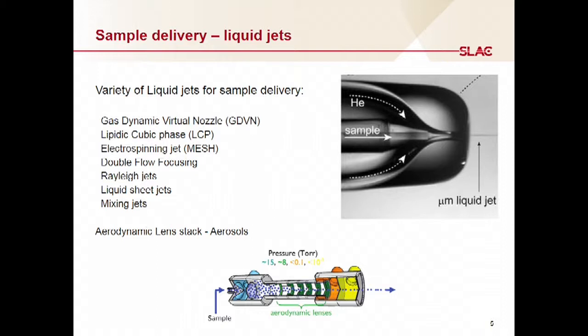There's also this aerodynamic lens stack, which is used very often for single particle imaging. What it does is it focuses aerosols. So if you want to have a solution of, say, particles or viruses, what you can do is you can aerosolize them. And then the aerodynamic lens stack has a series of pores which slowly focus the aerosol into a very, very small spot. Because for your hit rate, you want it to be very, very dense so you can have a lot of data. And if you have a very diffuse aerosol, you will never get the density that you need. So this aerodynamic lens stack is used in order to focus down your aerosol.